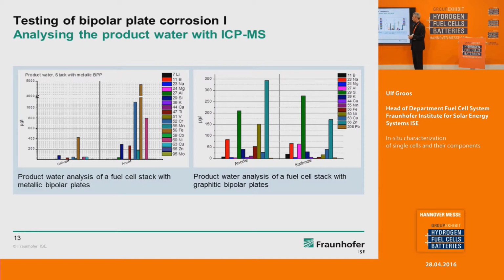We also analyze product water, for example. We have a measurement system called ICP-MS, inductively coupled plasma mass spectroscopy, which allows you to do element analysis of liquid samples. In this case, we collected the product water of a fuel cell stack with metallic bipolar plates, and what you see at the end is that you find a lot of iron in the product water, and as we have seen before, iron is very, very harmful to the membrane. So you should work on your metallic bipolar plate, or apply another anti-corrosion coating.